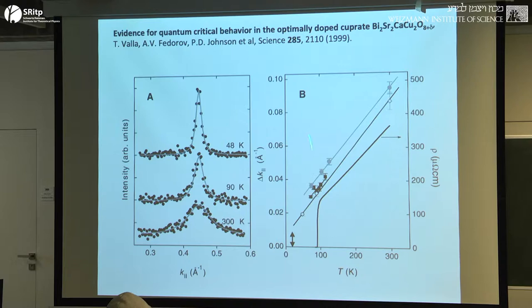On the other hand, if you look at the most coherent quasiparticle in the cuprate, so here's a famous paper by Peter Johnson on optimally doped bilayer BISCO, which has a much higher TC, and this is looking at the width in K-space of the quasiparticle propagating along the diagonal direction. And here he's plotted the width of that peak for several different samples as a function of temperature and compared it to the resistivity. And actually, if you take the Fermi velocity measured here and use it to compare to